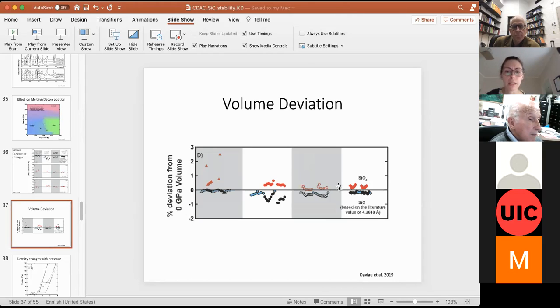It's also hard because these are from quench patterns from a map of the hotspot. So they're likely sampling different temperatures that were experienced in each different pattern. So this solubility of carbon into SiO2, if it is temperature dependent, we're probably sampling a lot of different temperatures in just this quench pattern across the hotspot. So it's kind of hard to pin down exactly what is contributing to that solubility, because there's different temperature conditions at these pressures. If that makes sense. Uh-huh. Sure.